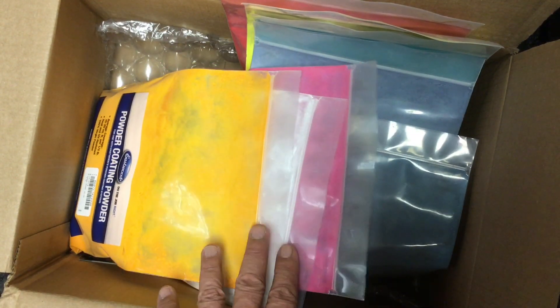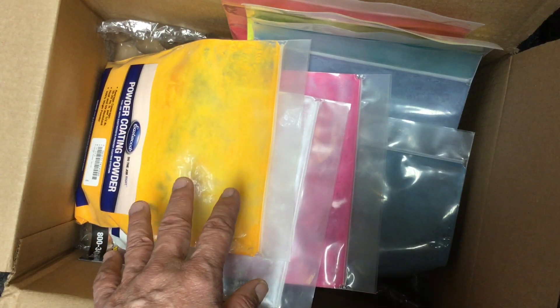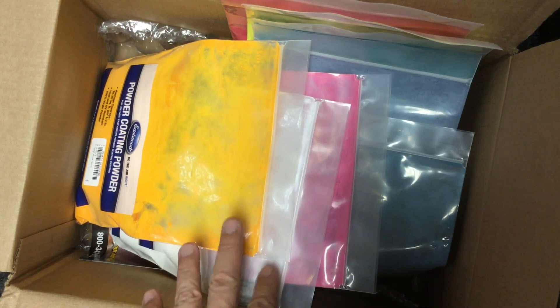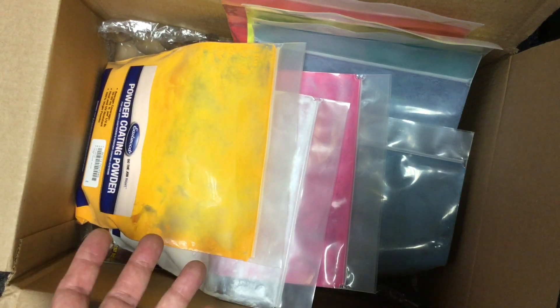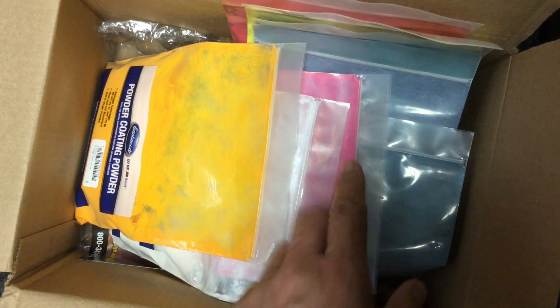One of my criteria is to select polyester powders — these are all polyester powders, not polyurethane and not epoxy polyester. You cure them in the oven at 400 degrees for 20 minutes, and that works for all of these. I chose polyesters because they tend to work fairly well; polyurethane may not work as well. These are tough, chip resistant, and coat well and thin. Also, these are reasonably priced — in the nine to thirteen dollars a pound range. There are other powders that cost as much as twenty dollars a pound, so I'm avoiding those.